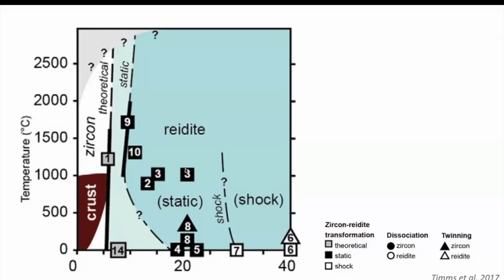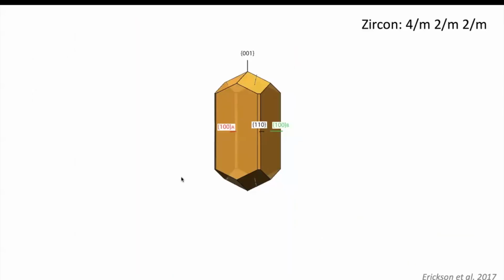High pressure multi-anvil, diamond anvil, and shock experiments have constrained reidite's formation to only high pressures. And once you get above this curve right here, there's almost no temperature dependence. This curve is really a kinetic effect that somebody did a paper about that came out after 2017, so it's not incorporated into this phase diagram. Zircon and reidite have been shown to have a consistent crystallographic orientation relationship in both experimental and natural samples.